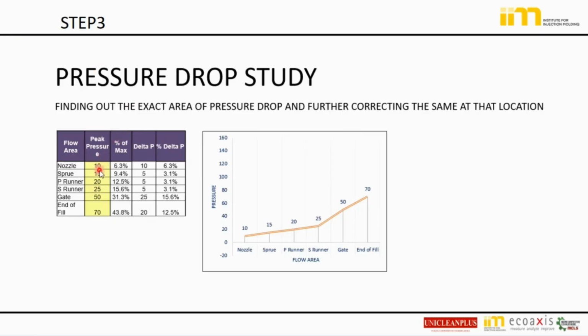So here we will be measuring the pressures in the machine. You can do different switchovers and fill the part up to the gate, up to the runner, up to the nozzle, and in the end to 98%. You note the pressures; the machine will show the peak pressure. The thumb rule says that for a cold runner, a normal mold, if you want consistency and to fill the part up to 98%, you should get 70 to 100 MPa, meaning 700 to 1000 bar. This is for a critical part, not for a cable tie or commodity parts. If you are able to fill at 70 to 100 MPa, you will get repeatability. If you are taking much more pressure, forget about consistency.